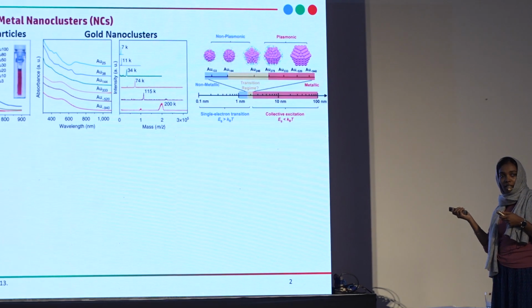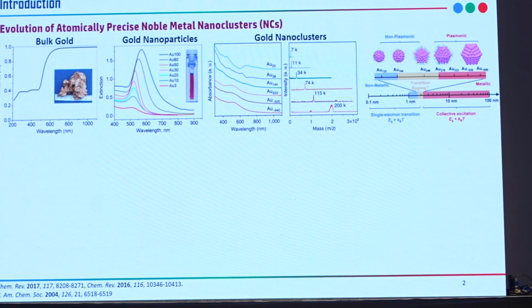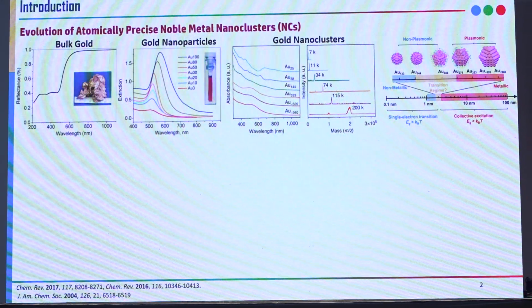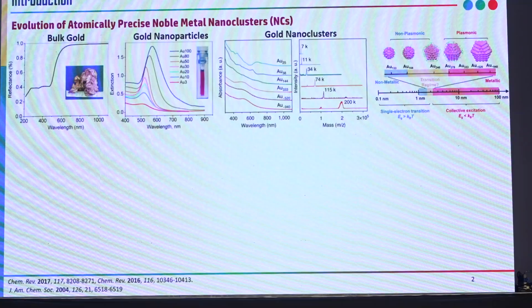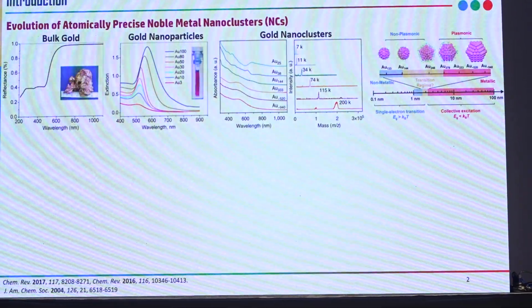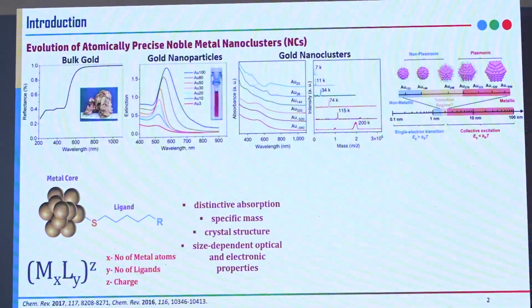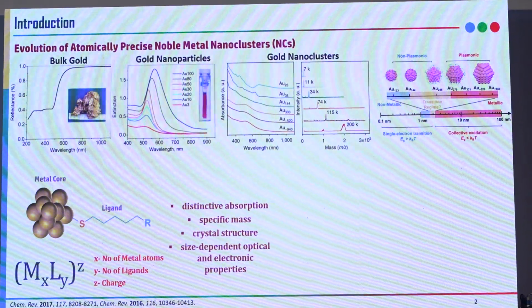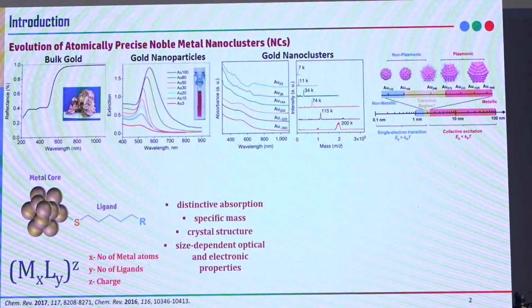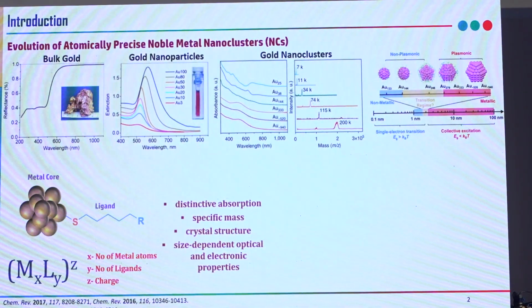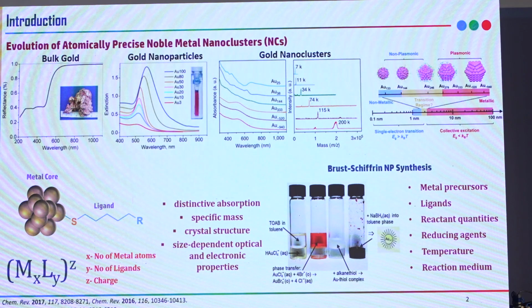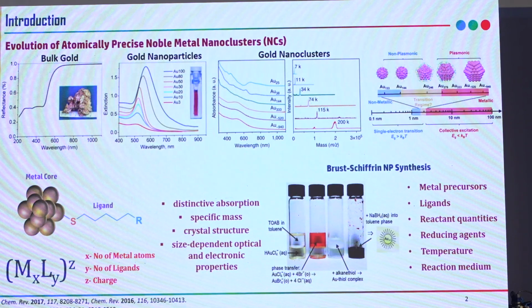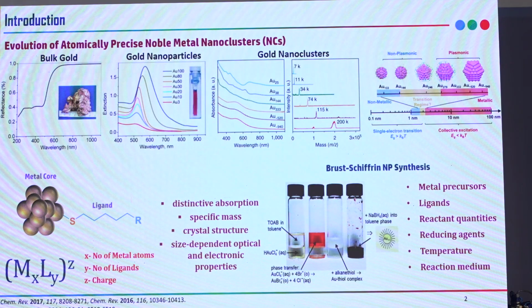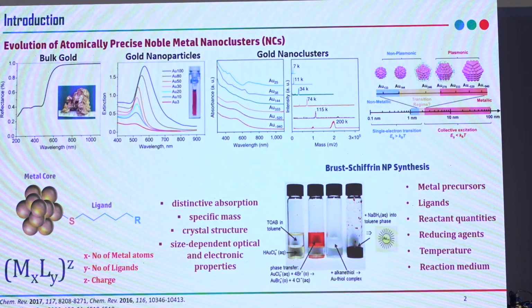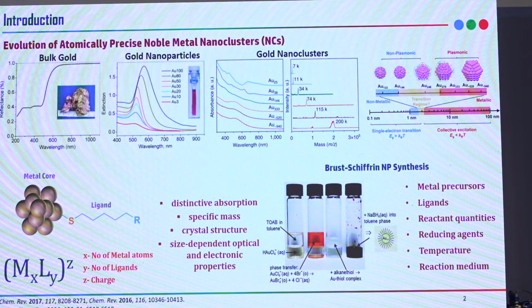Due to this quantum confinement effect, these nanosystems produce molecular-like transitions, and these sub-nanometer sized systems are known as atomically precise noble metal nanoclusters. These nanoclusters have a size of less than 2 nanometers, with a metal core and a definite number of ligands. Normally we synthesize these atomically precise noble metal nanoclusters in the lab. Previously it was a two-phase synthesis. Now we are using a single-phase synthesis, that is a modified Brust-Schiffrin method.